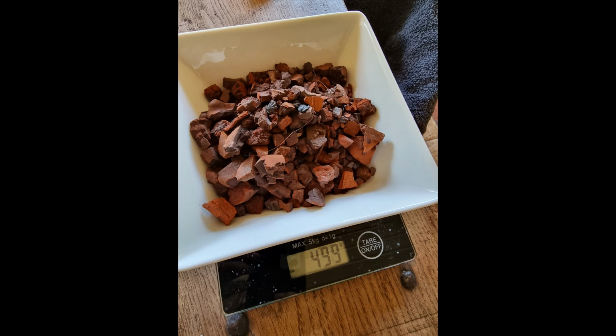Because of the unique way that this iron ore was formed, which is quite different from other types of iron ore, it is very pure, but also bears very specific trace elements. Chemical analyses have shown that the iron ore can contain as much as 90% iron-bearing minerals, and usually has some specific trace elements, particularly aluminum or alumina, because it is formed around a loam core, and also has 3.5% manganese oxides present in the ore.